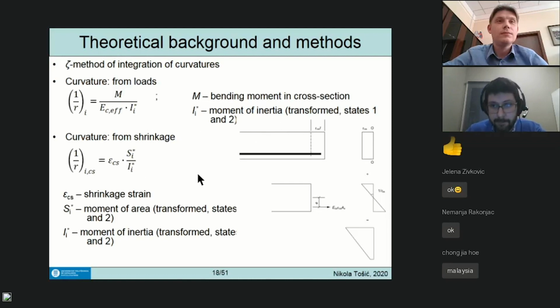Curvature from shrinkage is explained here for, let's say, sections without compressive reinforcement. The concrete would want to shrink, but the reinforcement would not, so it gets compressed while concrete gets tension. But there is the resisting force that causes an additional curvature. Of course, if there was the same amount of reinforcement in a symmetrically reinforced cross-section, there would be no curvature from shrinkage, but this is not how we reinforce slabs or elements in bending.